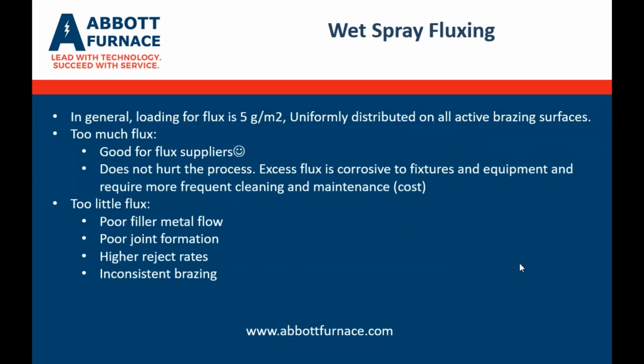So now you have a clean part. You're looking to flux the part. In general, the loading for flux is about 5 grams per square meter, uniformly distributed on all active brazing surfaces. Too much flux, obviously good for flux suppliers, doesn't really hurt the process itself, but excess flux is very